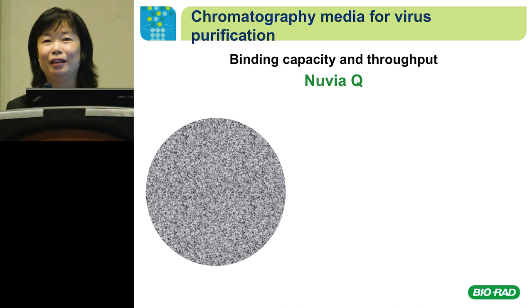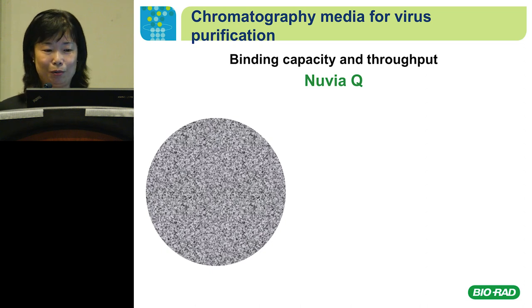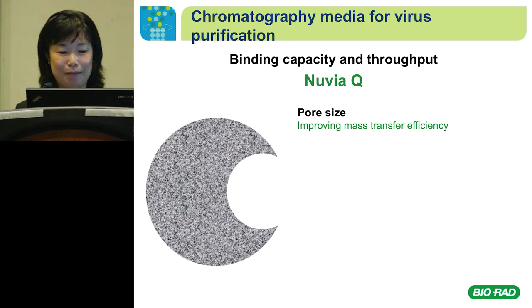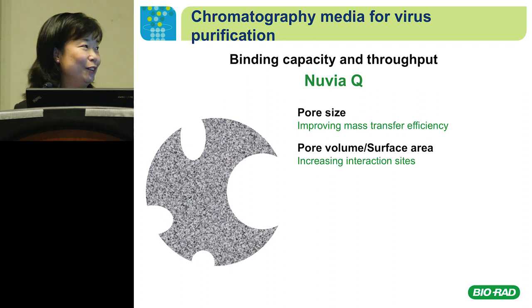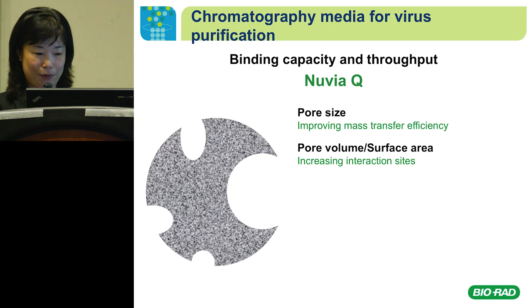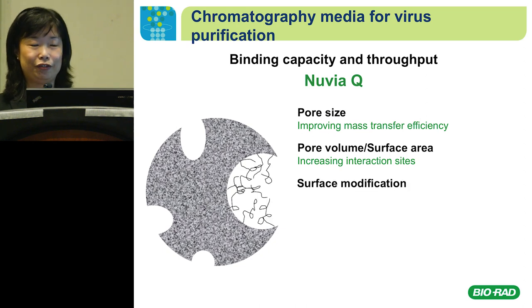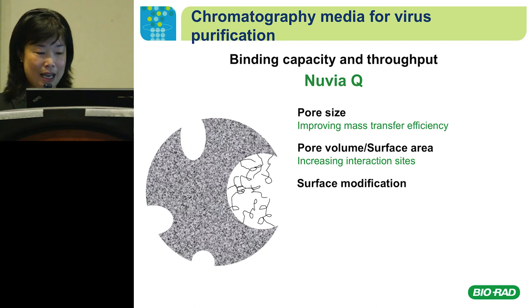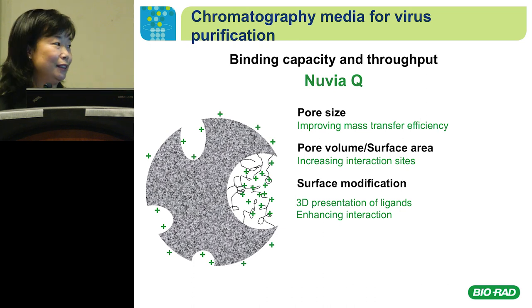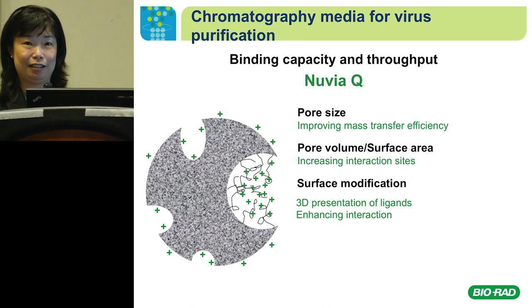The problem with SEC is that it's very slow and takes a long time, making it hard to improve throughput when dealing with large volumes. For resins, the first thing we need to fix is enhancing diffusion and mass transfer efficiency. To do that, we create larger pores so the virus particle has more chance to enter. We also create surface area for binding — the interaction between target molecules and the resin functionality is two-dimensional. To further improve binding capacity, we immobilize polymers inside the pores.